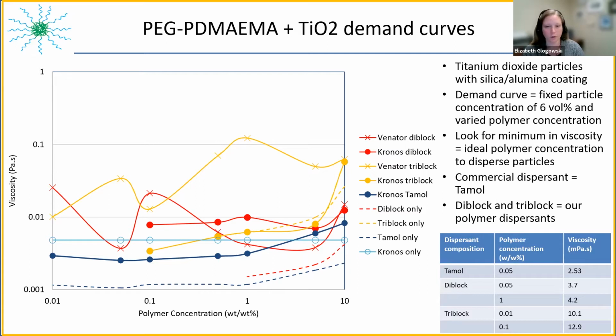So what we expect, and what you can see with the pure dashed lines, is that as we increase the polymer concentration, whether it's our synthesized polymer or a commercial dispersant called TAMOL, as you increase that polymer concentration, you see an increase in the viscosity. What we're looking for and what we expect is to have a high initial viscosity when we first mix a low polymer concentration with the fixed particle concentration.